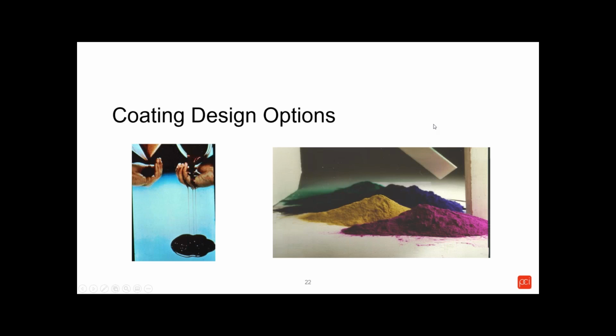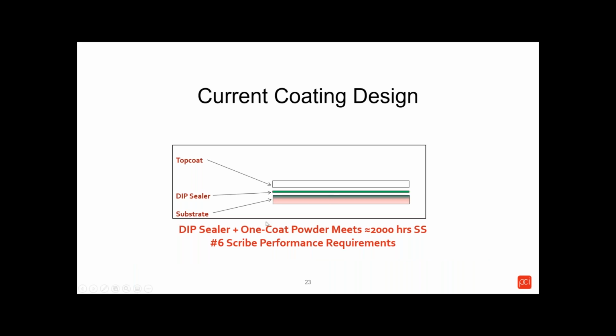Okay, so what were the coating design options available to meet this particular client's requirements? Let's take a look at those. The current method of operation was to use either stainless steel or aluminum, as we said, as a substrate. They applied what was called a DIP, dried in place, not a dip. DIP stands for dried in place, not an immersion process. So they applied a dried-in-place sealer onto that substrate surface after cleaning it. And then a single top coat met their performance requirements, which we estimated around 2,000 hours salt spray on aluminum and to a number six scribe performance requirement. So that was our target goal.